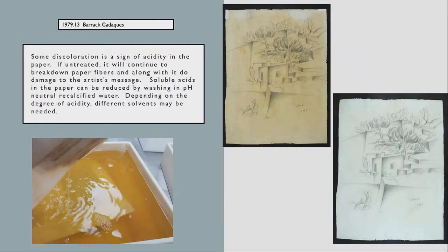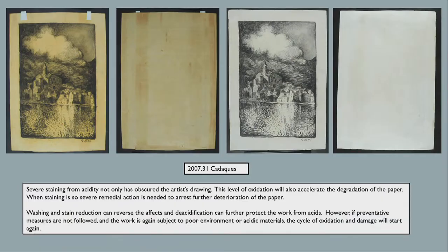If you look at the bottom left, this is washing something with soluble acid. Look how much discoloration comes out. That's what's contained in that paper. And if it's soluble, you can wash it out. So some discoloration is a sign of acidity in the paper. If untreated, it will continue to break down the paper fibers and along with it, the damage to the artist's message, right? Soluble acids in paper can be reduced by washing in pH neutral recalcified water, keeping the pH level and giving it a little bit more calcium in there. Depending on the degree of acidity, different solvents may be needed if it's beyond solubility.